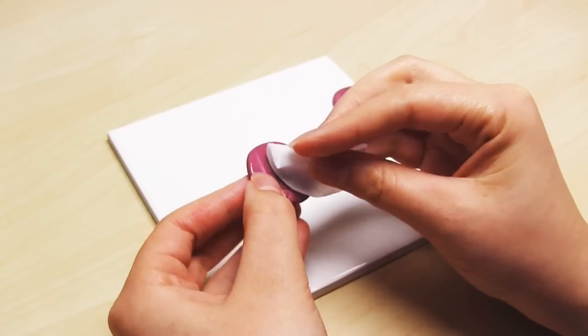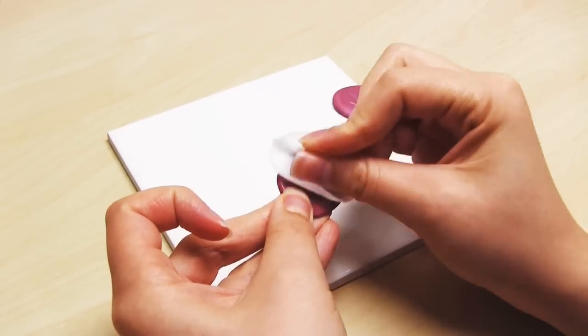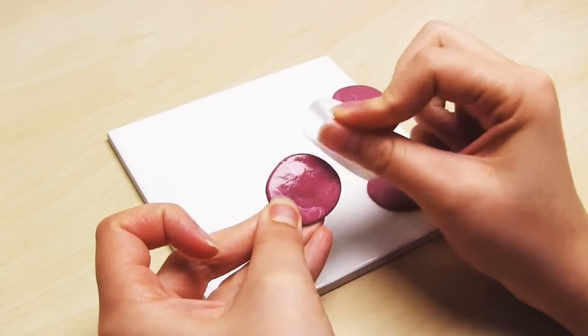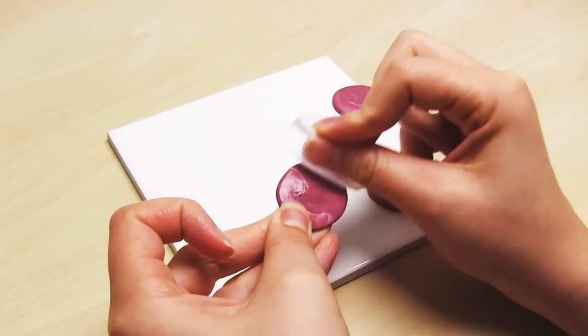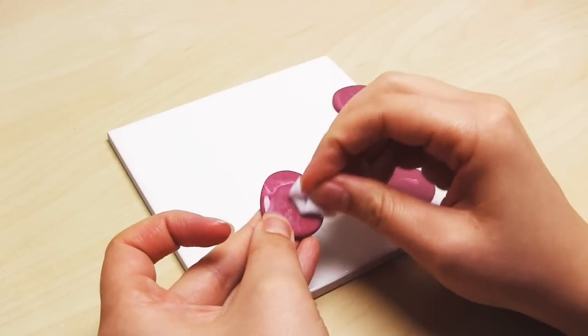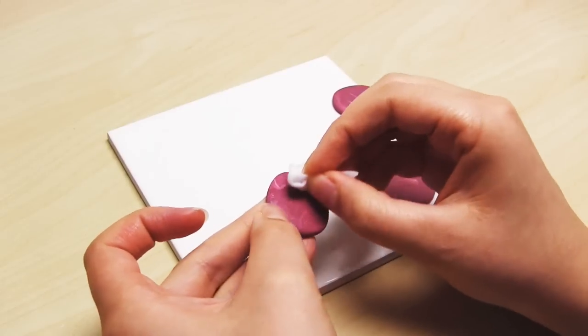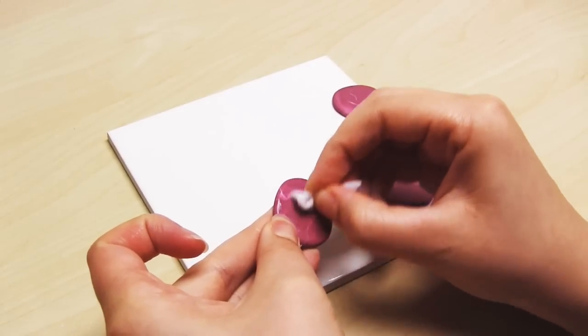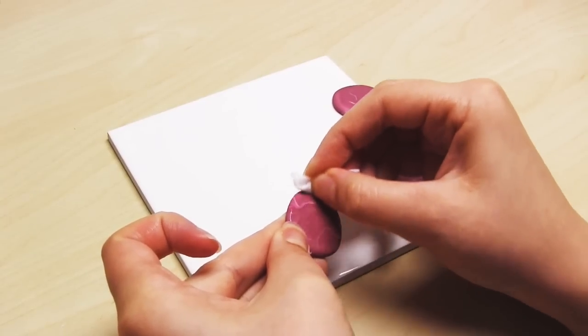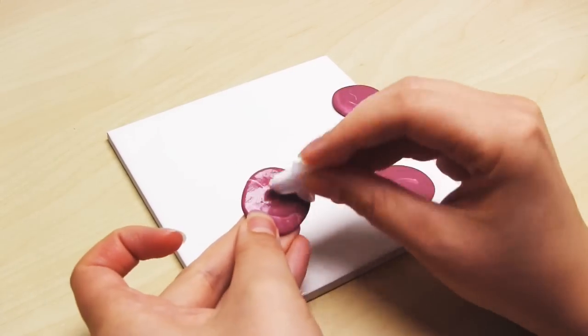If the acetone doesn't work for you because the lint or dust is too embedded inside the clay, then the other options you have are to A. Use sandpaper on the surface of the clay until you get down to where that piece of hair or lint or dust is, and then you can remove it. B. You can paint the clay, so basically you're covering up any of the bits that are embedded in the clay. The best paint to use on clay is acrylic paint. Or C, you can texture the clay in order to disguise any little bits that are embedded in the clay beneath. So you could use a toothbrush or a sponge, for instance, to add a texture.